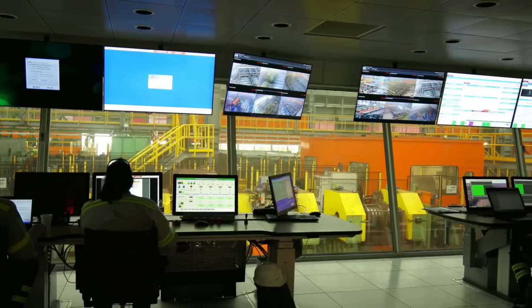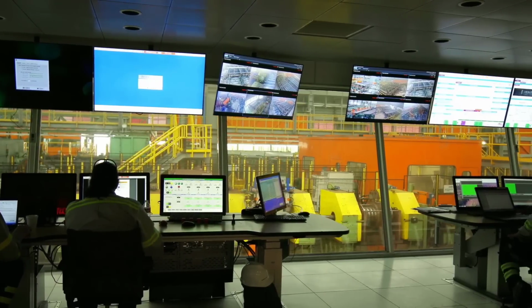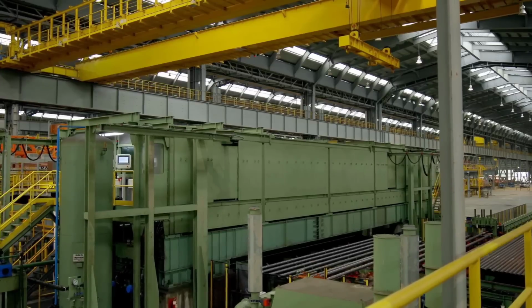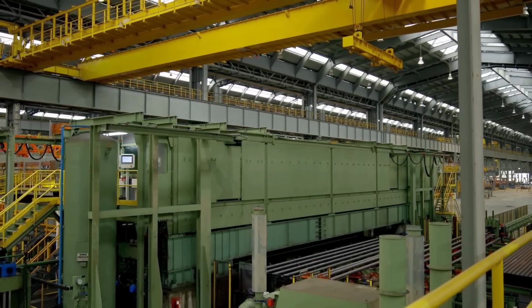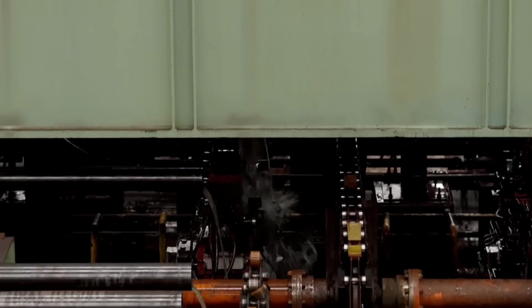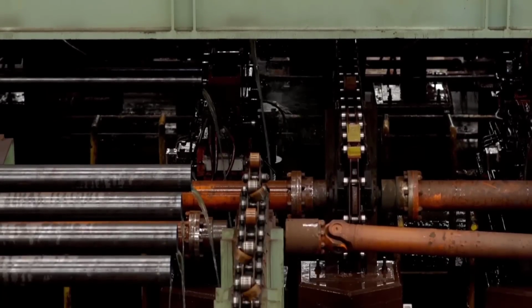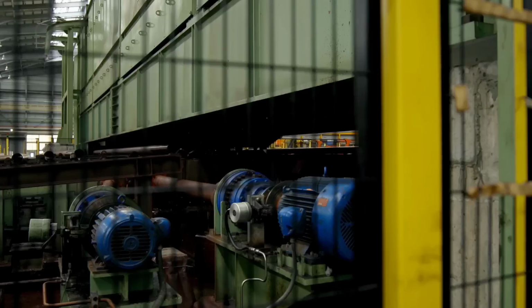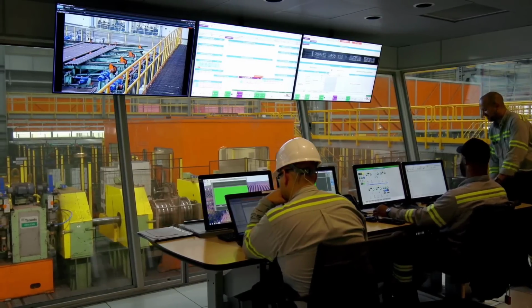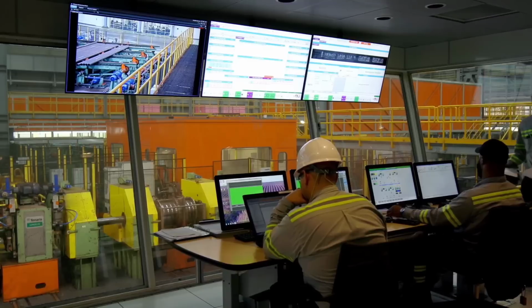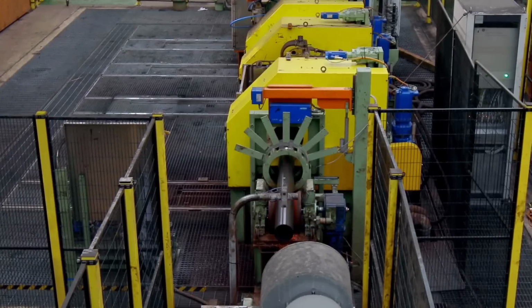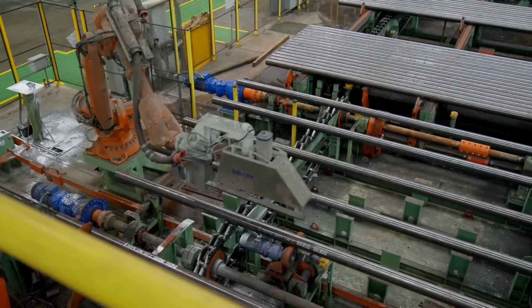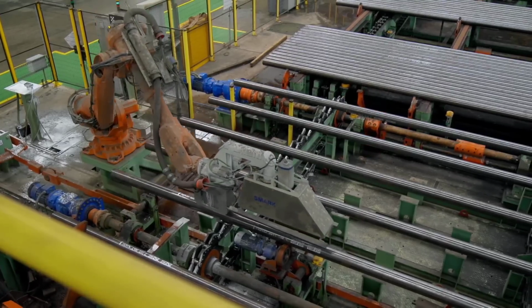In the final stage, the pipe goes through rigorous testing and verification to ensure it meets Tenaris's stringent quality standards and the specific requirements of the customer. First, hydrostatic testing is performed to guarantee that the pipe can withstand specified pressure requirements. Next, an electromagnetic inspection is conducted to detect defects internally and externally. Ultrasonic testing is then employed for precise wall thickness measurement.